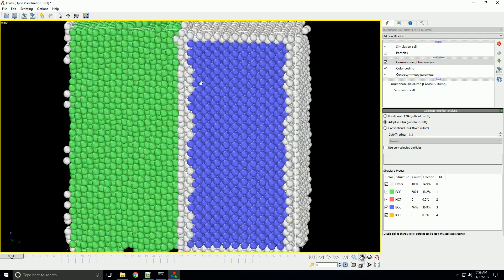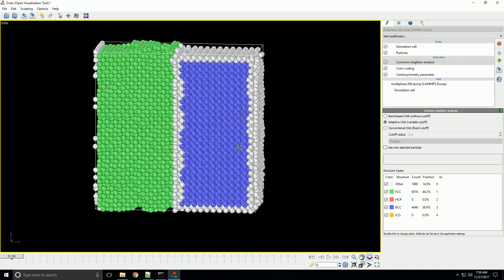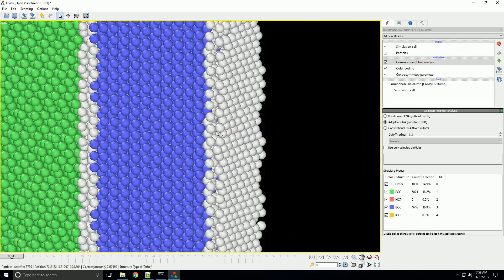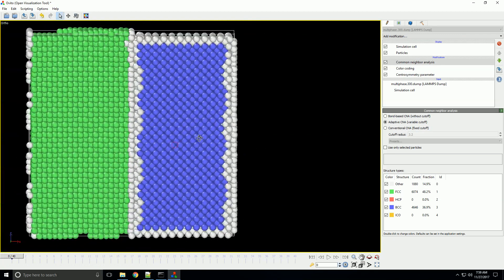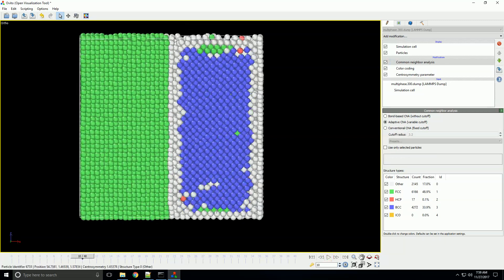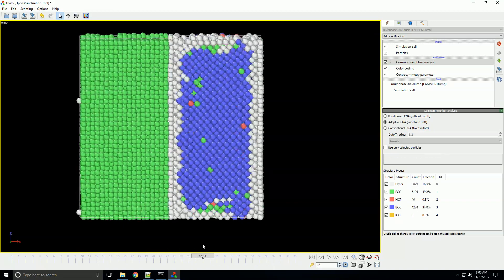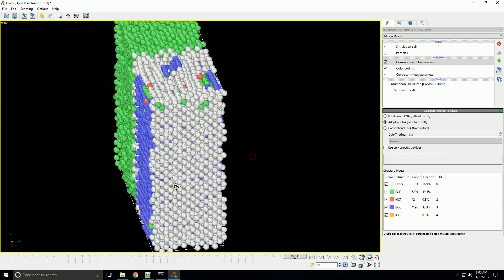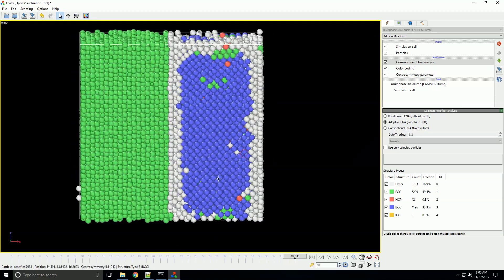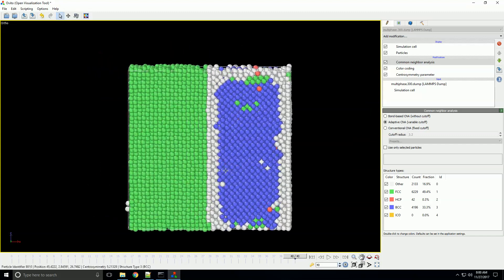The stuff around the edge is marked as 'Other' because it's not in a defined state based on its neighbors. If we scroll along the time series, you can start to see random FCC and some HCP atoms appearing inside the BCC phase because it's just not stable and is shaking up a lot. I didn't let this run long enough to fully transform, but you get the idea that it would start transforming into FCC.